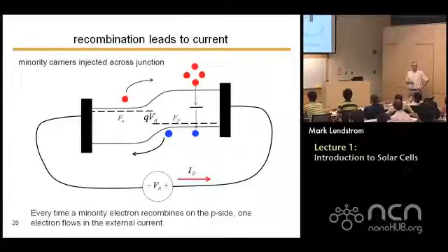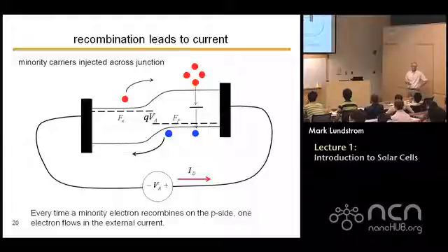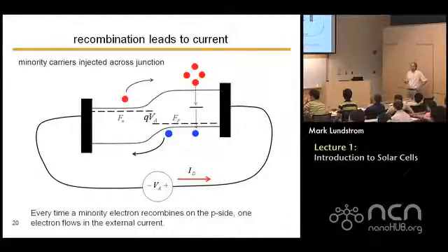Even though silicon is very, very pure, for solar cells you like to use less expensive silicon, so it's not as pure as it could be, but it's still very good. But there are defect energy states inside the band gap. An electron could hop down into that and then hop down again and fill up a whole state. So that's a dominant way.